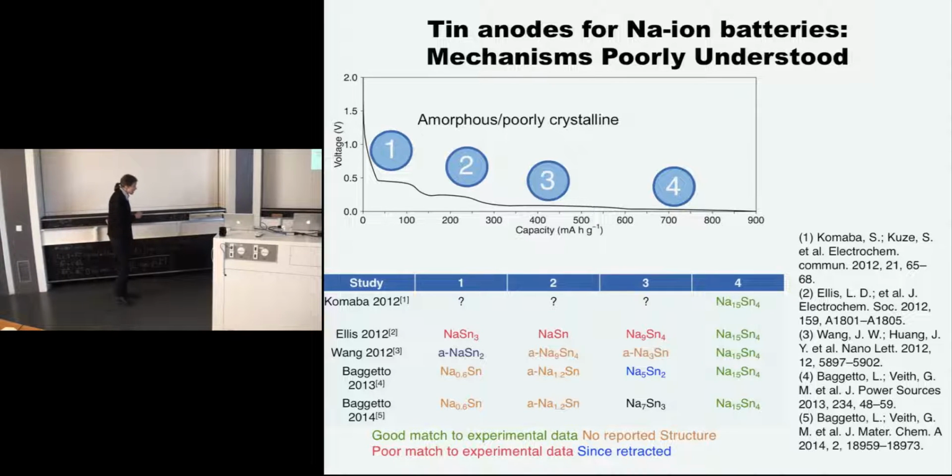For sodium-ion batteries, there's no good battery anode material. Sodium can't intercalate into graphite. Lithium intercalates into graphite, potassium intercalates into graphite, but if you try to intercalate sodium into graphite, you plate sodium instead. So there's a push to develop alternative anode materials for sodium. The best materials out there are hard carbons, which are disordered carbons, but they have lower capacities than graphite. Tin does a good job, although it has problems associated with breakdown of electrolytes.